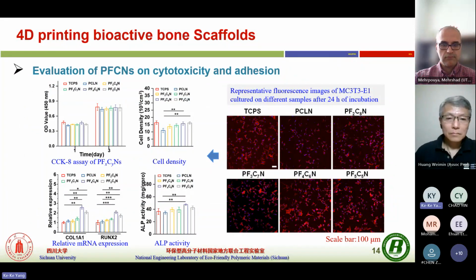We also evaluated the cytotoxicity and cell adhesion of this scaffold. The CCK8 assay showed good biosafety, and cell density increased with the introduction of the PPF segment, showing upregulation of mRNA expression.